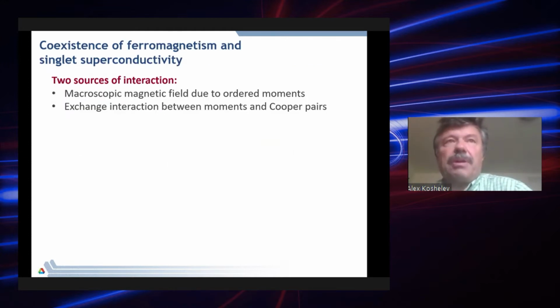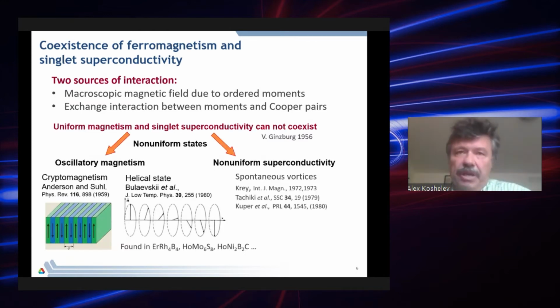Actually, people started to think about the possibility of coexistence of ferromagnetism and superconductivity long before actual materials were discovered. There are 2 sources of interaction. There are, first of all, macroscopic magnetic fields generated by the ordered magnetic moments, and there is exchange interaction between moments and Cooper pairs. And both of these mechanisms make coexistence of uniform magnetism and superconductivity impossible. This was pointed out a long time ago by Vitaly Ginzburg in '56. And at least one of the states should become non-uniform.